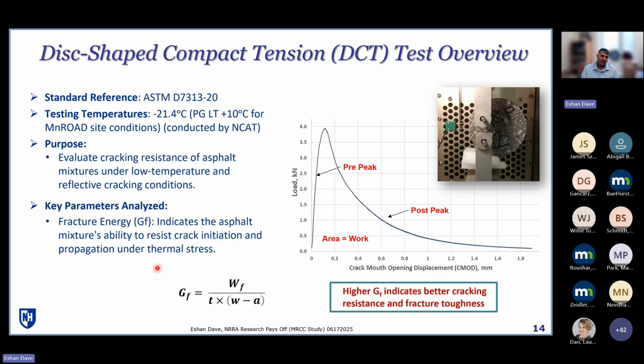Now, keep in mind that with MnDOT or MnROAD, we are at a cold climate location. All the tests that I talked about until this point, especially the cracking tests, are done at intermediate temperatures. And that's great when you are simply looking at the general response of mixes, especially in warmer conditions. But at a low temperature, you obviously need to know what type of embrittlement these mixes would undergo as things cool down. That's one part.